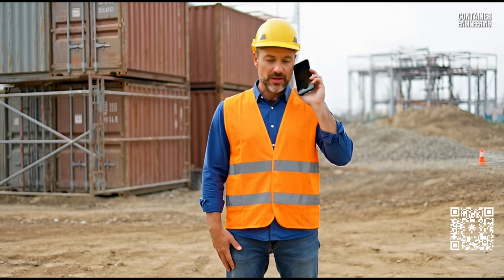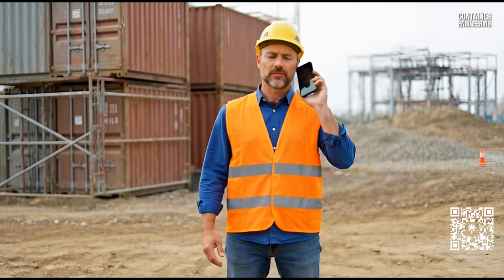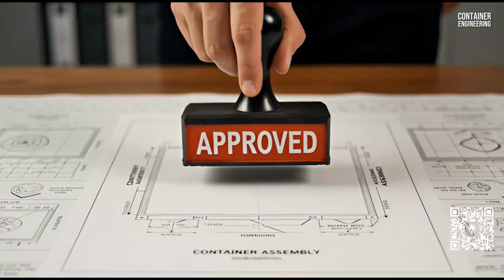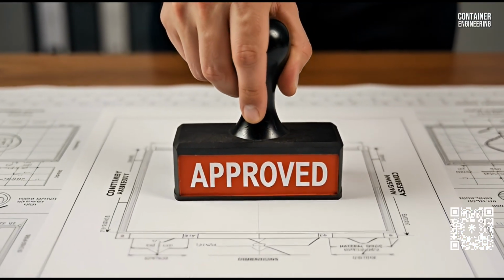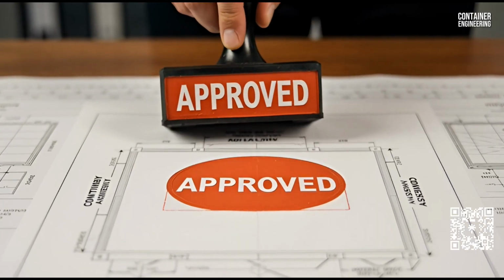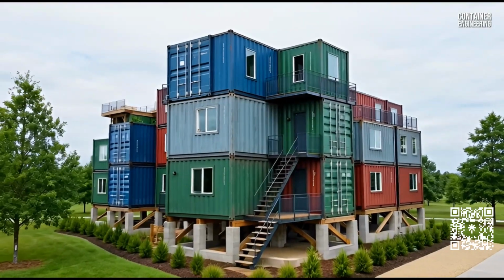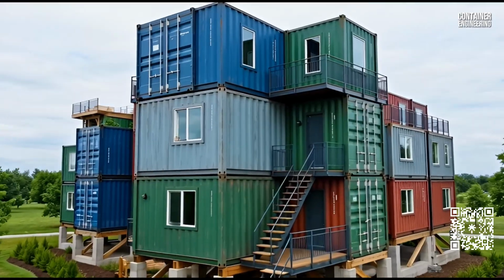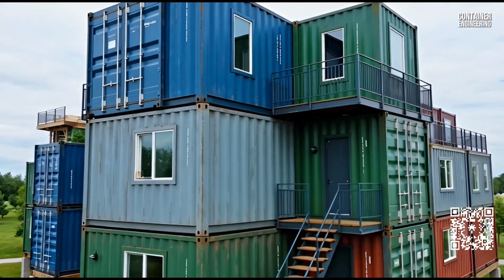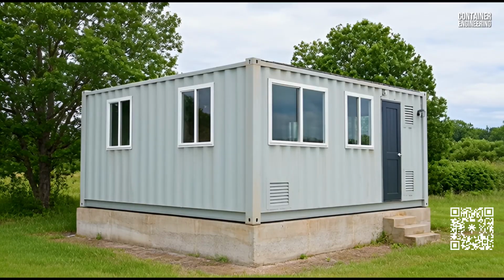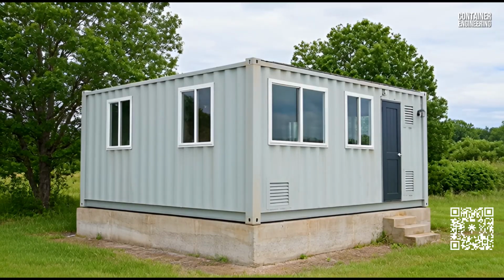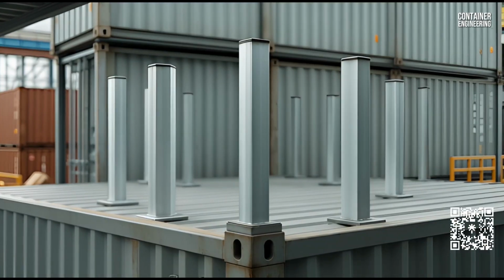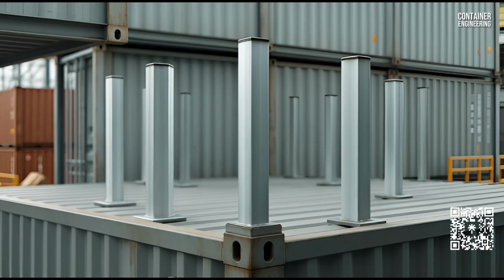When you apply lateral force, the corrugations want to buckle. The container relies on the rigid corner posts and the top and bottom rail frames to resist racking. Here's where people make the fatal mistake. They cut openings for doors and windows, which eliminates the racking resistance. A standard 40-foot container has an effective lateral stiffness of approximately 12 kips per inch when intact. Cut out a 10-foot section of wall for a sliding glass door, you've just reduced the lateral stiffness by 60 to 70% in that direction.